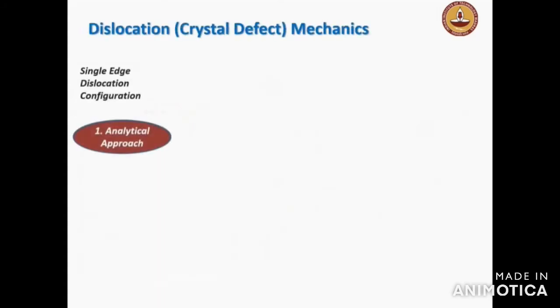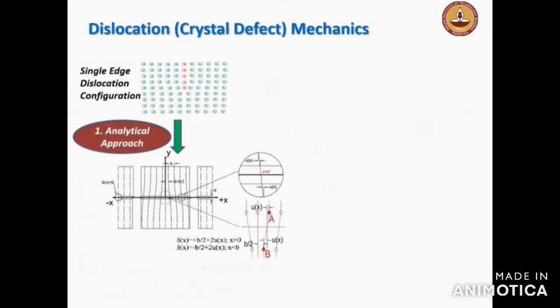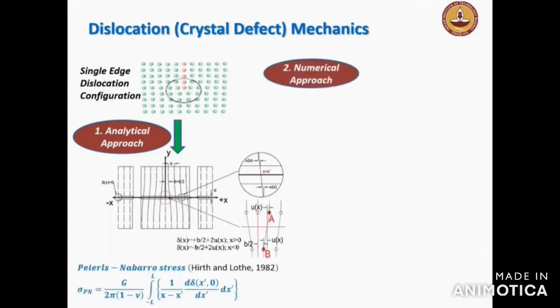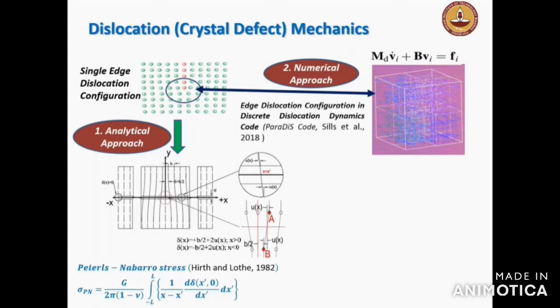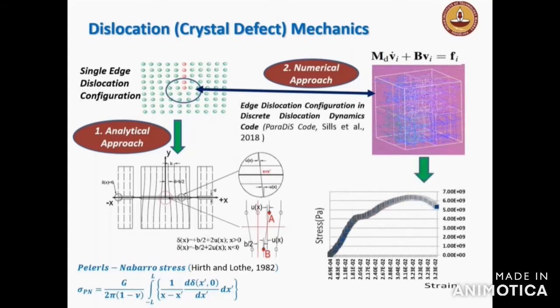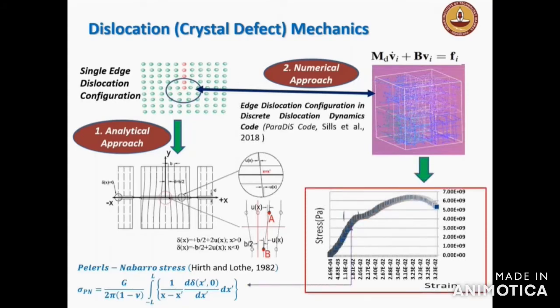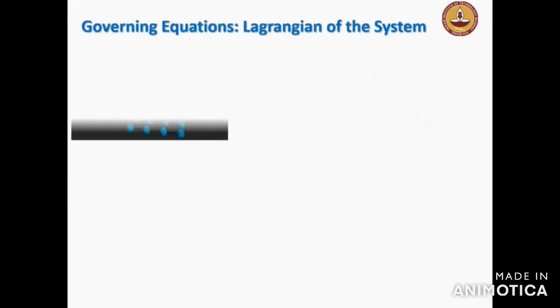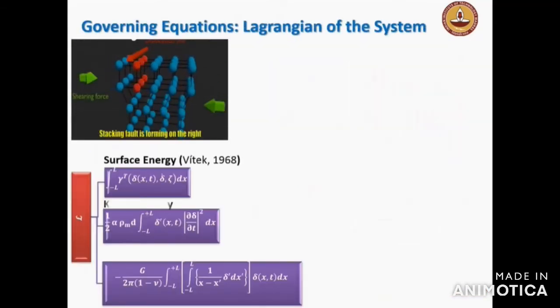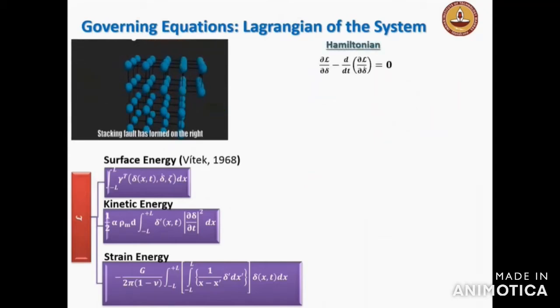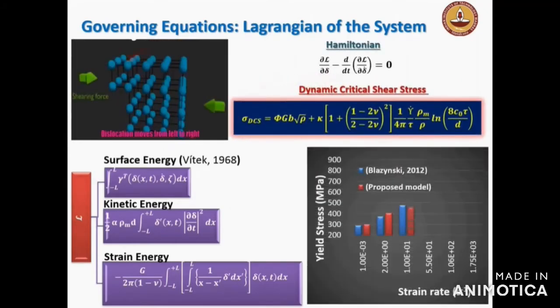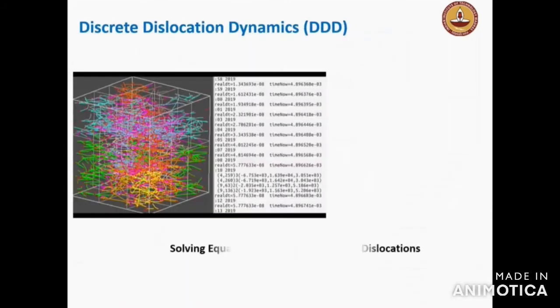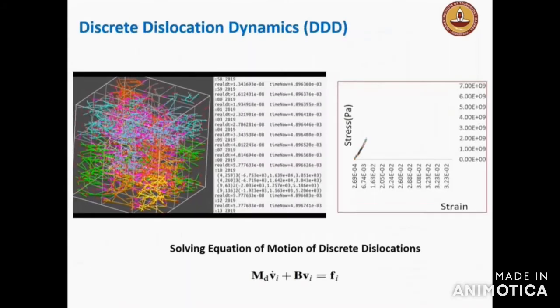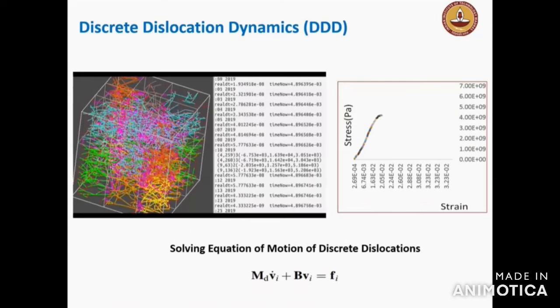There have been several attempts to investigate rate-dependent strengthening mechanism of metals at length and time scales associated with mechanical experiments, at length and time scales associated with deformation of crystal structures of metals, as well as at atomistic levels. Here at our SMILES lab, we investigate the micromechanics of dislocation motion and thereby understand the physics of the problem observed in experimental levels, especially the strength enhancement mechanism in metals under high strain rate deformations.